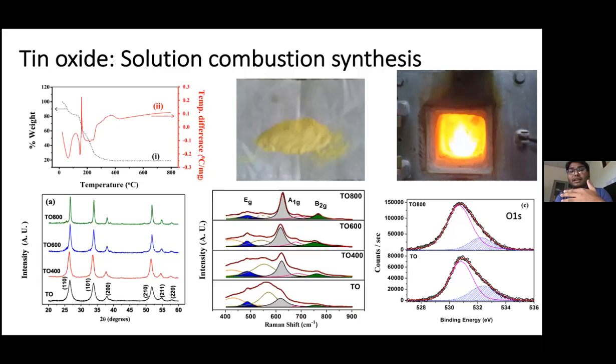So you can see in the XPS spectrum also, we saw some kind of peak. XPS results from the core level photoemission from the sample. So you shine the material with X-rays, and you get a photoelectron emitted from the material. Since it is coming from characteristic energy core levels, you can measure the kinetic energy of that emitted photoelectron, subtract it from the incident photon energy, and you get the binding energy of that electron, which is a fingerprint of a particular element composition.